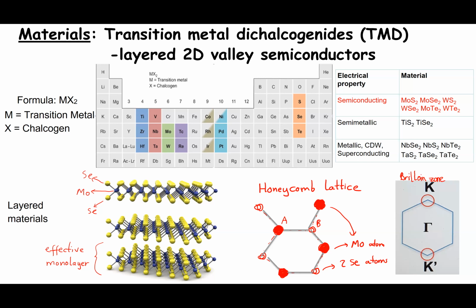And the bonds between these atoms are covalent, very strong, and have some ionic character. But the bonds between the layers are van der Waals, so it is relatively easy to go down to a monolayer by the usual exfoliation. Okay. And given this lattice structure, one would expect that there would be interesting physics, not necessarily, but it could happen at the high symmetry points, K and K prime, of the Brillouin zone.